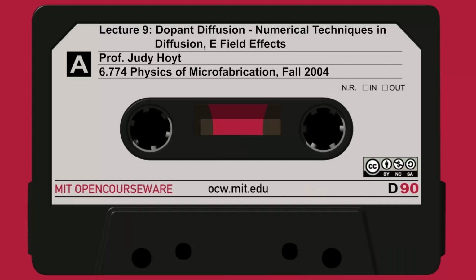If that multiplier gets too large, the whole method breaks down, becomes unstable, and you get absolutely meaningless solutions. So if you're doing this numerically, make sure you adjust your time step delta t to be small enough so that this holds, and your delta x to be of appropriate size with respect to delta t, so that you don't leave the numerically stable regime. It's a very powerful technique. It's very simple. That's one of the nice things about it.